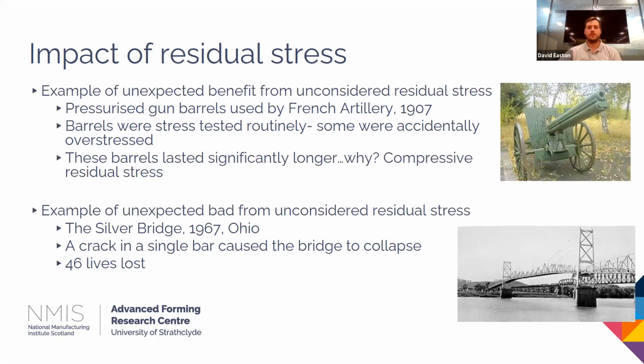So just to get a couple of specific looks at residual stress and why it's important that we relieve it in some circumstances. Gun barrels, so back in 1907, gun barrels would quite frequently fracture during operation. And then it was found that certain barrels actually weren't fracturing, and it turns out these were ones that had accidentally had their residual stresses beneficially modified. So this is an insight into how managing residual stresses can result in better performance.